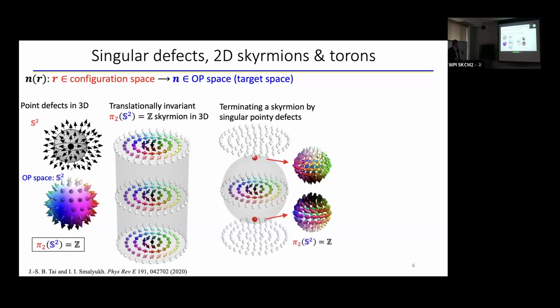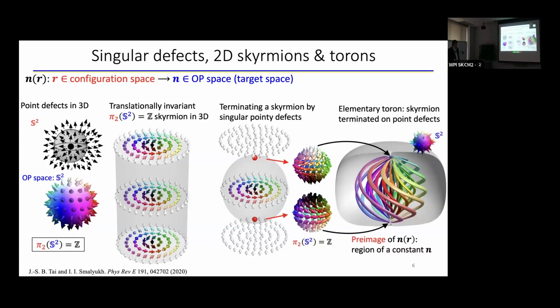And what's interesting is that we can form hybrid structures that we call torons, where a skyrmion tube can terminate on point defects of the same homotopy class, with the same Z integer number that describes how many times such a field configuration wraps the order parameter space as you do some mapping. And then these topological solitons, torons, that we form in this case have singular point defects and non-singular skyrmionic structures that for every single point on the order parameter space S2 have these peculiar preimages that have a chiral pattern to them, as you can see visualized in here,